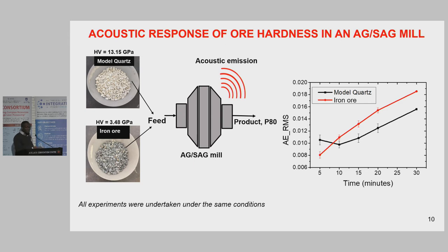This result is in contrast to when the same ores were subjected to AG-SAG mill operation. So model quartz and iron ore were put under the same conditions in a laboratory AG-SAG mill. Here we saw that the acoustic intensity increased continuously with increasing grinding time and also with reducing size fraction. The opposing results that we saw for the two ores in the laboratory ball mill and in the AG-SAG mill can be explained by their different operating or working conditions.